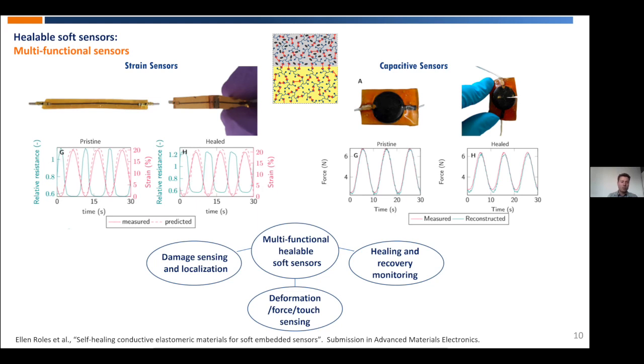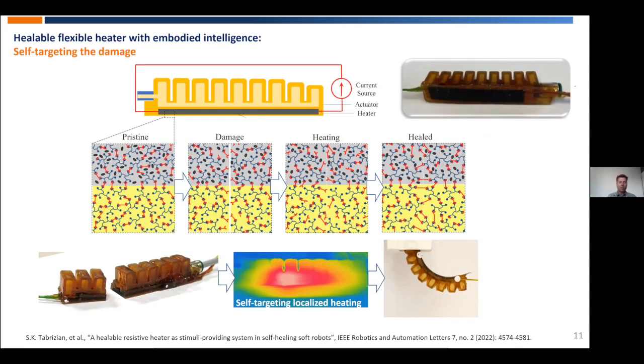Now, the next example that I want to show is that we also make self-healing heaters, which are flexible. So they're also composed of self-healing composites, which are electrically conductive. So we made this heater and we embedded it in a finger actuator. And you can cut the complete actuator and the heater in two, and you can put it back together. And then you have recontact.